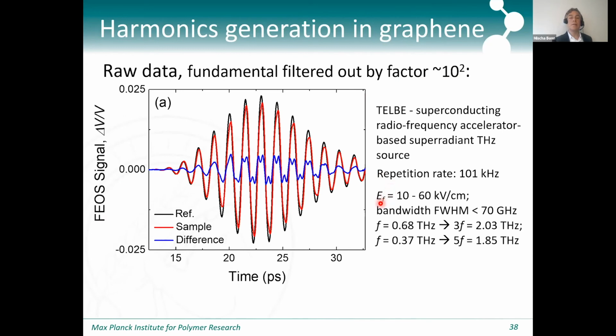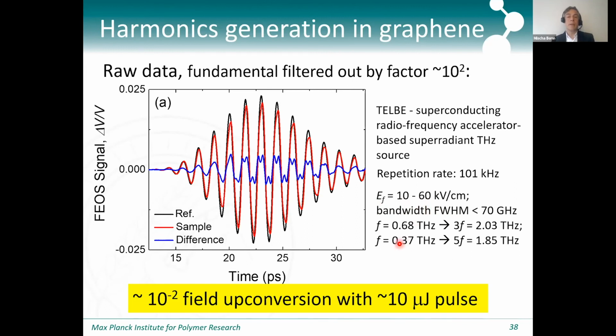And again, these are not very high field strengths. These are field strengths of tens of kilovolts per centimeter. And so the remarkable thing is that we get about 1% conversion in terms of field. So that's 10 to the minus 4 conversion in terms of intensity with a 10 microjoule pulse. The nice thing about these free electron lasers is that you can get a lot more pulse energy.